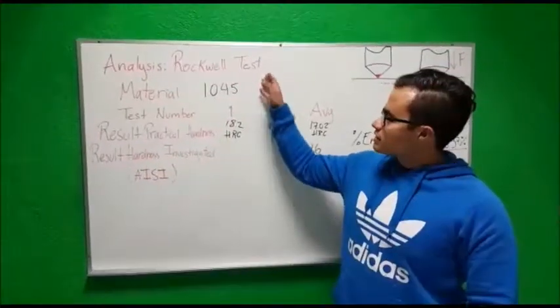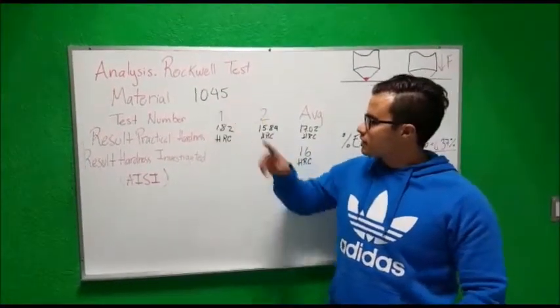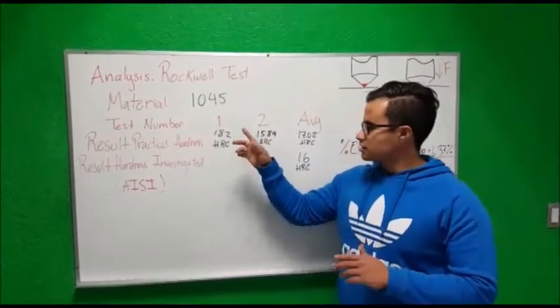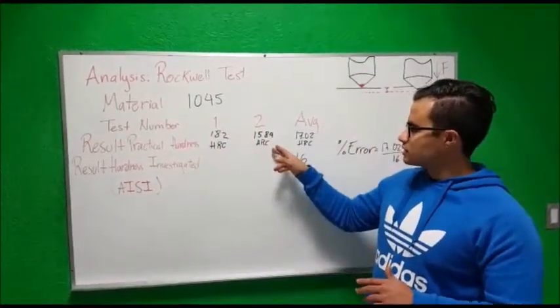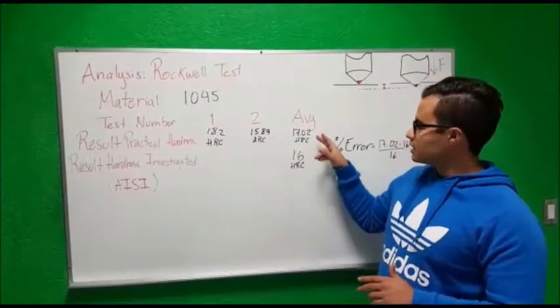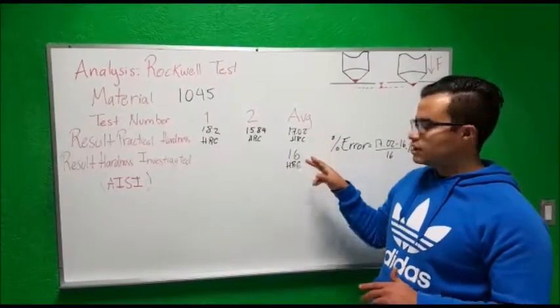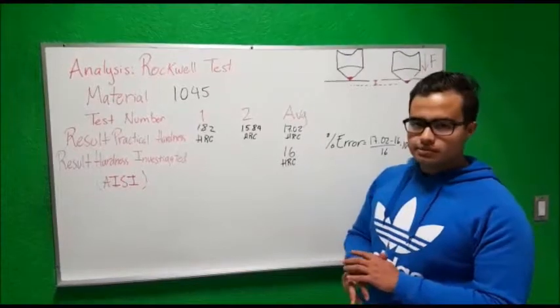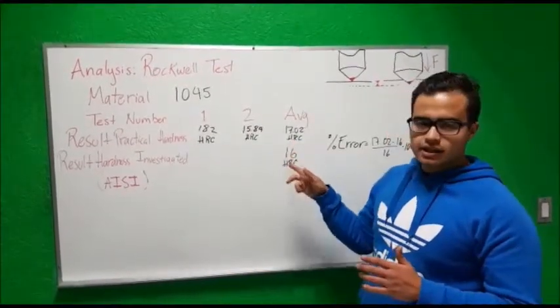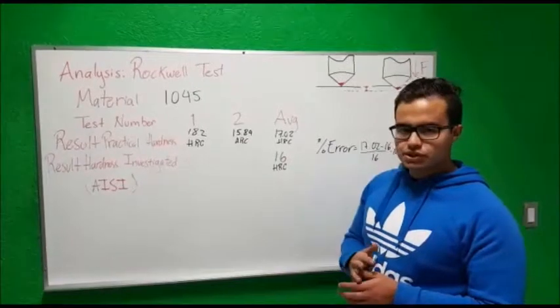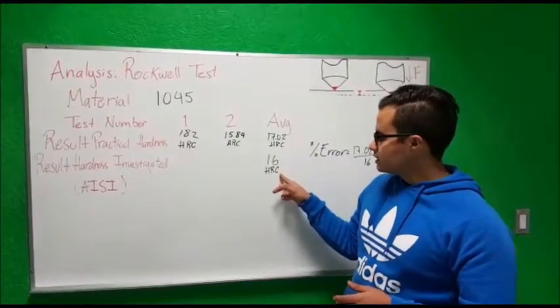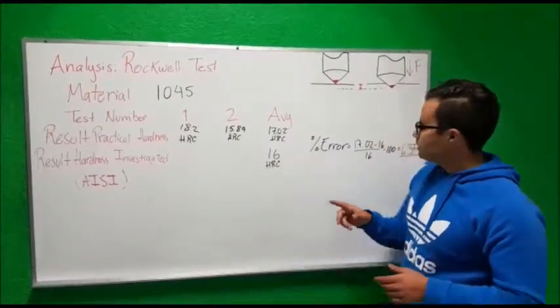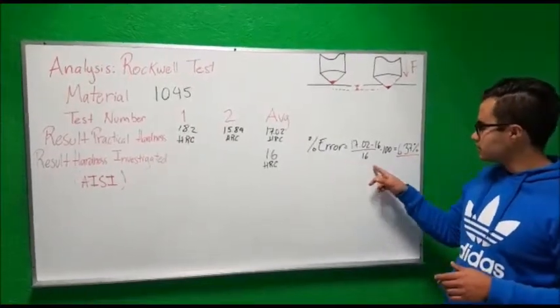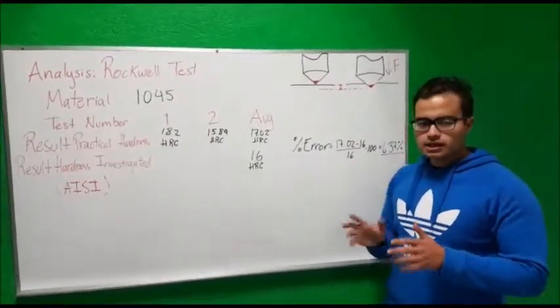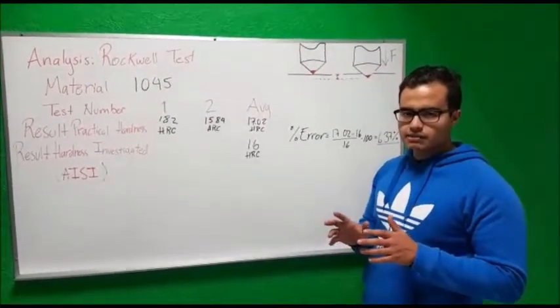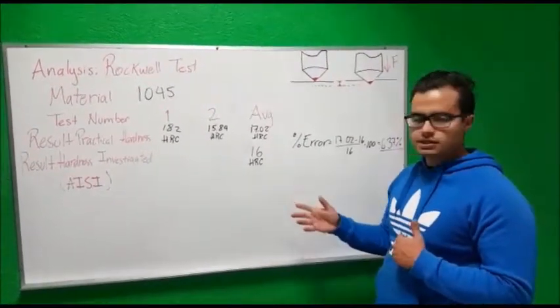Okay, for the Rockwell test in the steel 1045, we got these results. The first test was 18.2, the second was 15.84, giving an average of 17.02 HRC, where HR is the identifier for the Rockwell machine, and C is the scale we were using. The result gave us an error of 6.37, which is inside a valid range, so our test was a good one.